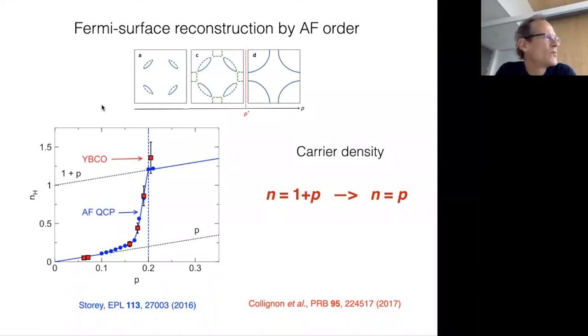Yeah, so there's one theoretical proposal, which I went through very quickly, but this is basically a scenario that Allan MacDonald has investigated. He's shown that you can get skew scattering of phonons off charged impurities. If you have, let's say, an oxygen vacancy or oxygen impurity, because of the local electrons it will actually be charged and will generate locally a Lorentz force effectively. And that will cause phonons to skew scatter, and it will produce a thermal Hall effect. In principle, you may have noticed that a lot of the materials we study here are oxides, so oxygen vacancies are a clear possibility. However, there are a few things that argue against that.